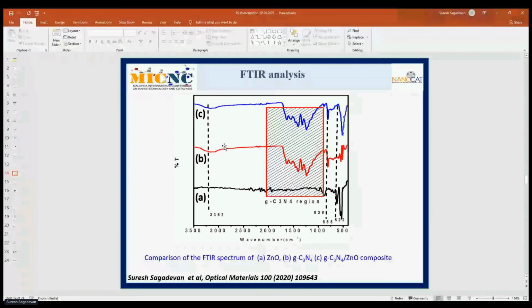From this FTIR analysis, you can see the peak at 1640 cm⁻¹ can be associated with the C=N stretching vibration, while the other peaks in the range of 1000 to 1400, at 1242, 1320 and 1400, can be linked to aromatic C-N stretching, and the band at 828 cm⁻¹ is due to the out-of-plane bending vibration of the CN heterocycle.